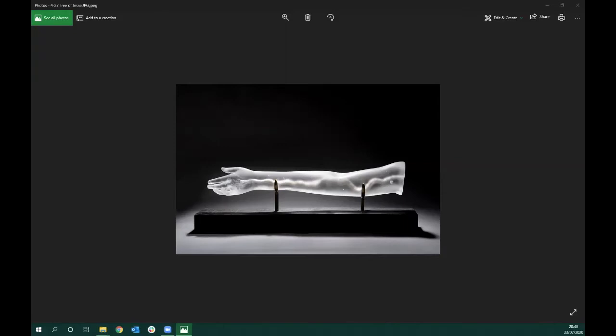And by making that ivy branch in a pre-made investment core and then suspending it inside a wax of an arm, I was able to cast the two things in one. So I was able to get the glass to flow down from the point where the shoulder is in that piece all the way to the tips of the fingers, and effectively encapsulate that ivy root in the inside of the piece. So that was a piece that I exhibited at the British Glass Biennale about 2004.